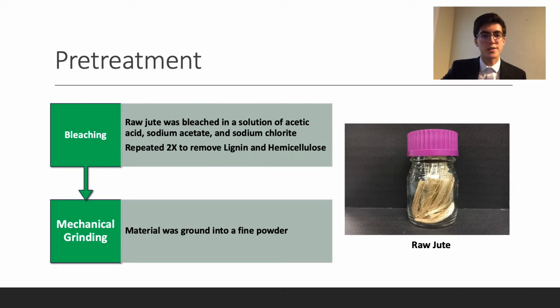To go about addressing the objectives, I synthesized 3 separate cellulose sulfate materials based on 2 reactions that were run in parallel to each other. Now, before conducting these reactions, a pretreatment protocol was necessary, where raw jute was bleached in a solution of acetic acid, sodium acetate, and sodium chlorite, and this was done 2 times to remove lignin and hemicellulose. Following the bleaching process, there was a mechanical grinding process which essentially broke the raw jute into very small, fine pieces so that the sulfonation reactions could be more efficient.